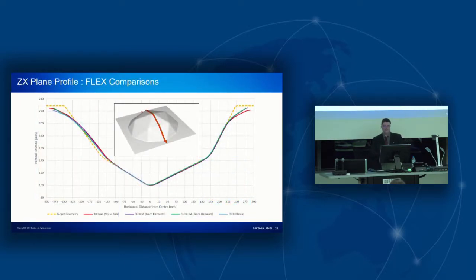And so here's what we see. This is a cut through of the part. And so what we have is in the yellow dashed lines, we have the actual geometry itself, the target geometry. It's important to note that's not what we're trying to match. So what we're trying to match is the red curve. And the red curve is a cut through of the actual scan profile.